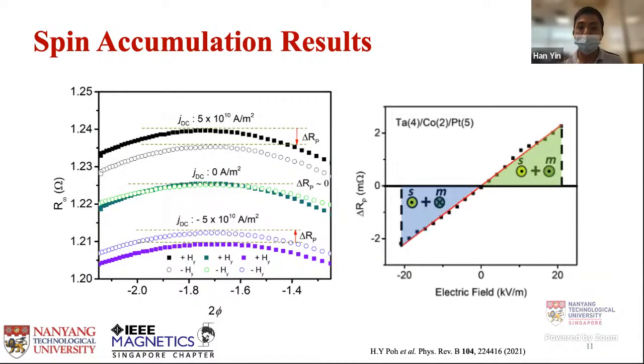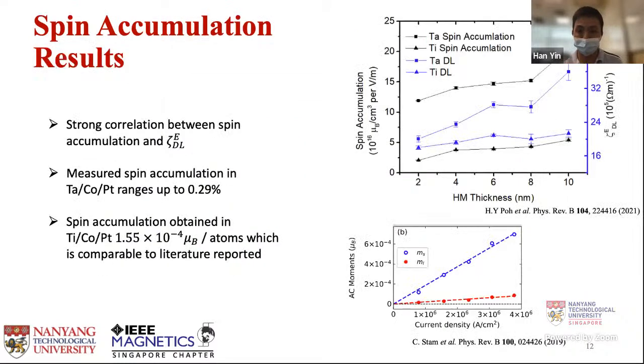So if we sweep a range of DC current, we can observe a linear change in delta RP, which is as expected, since current is proportional to the accumulated spin. Our experimental result is summarized on the top right-hand corner of the screen. The black and blue points represent the spin accumulation and damping-like field respectively. At first look, we can observe an obvious correlation between spin accumulation and the damping-like term.